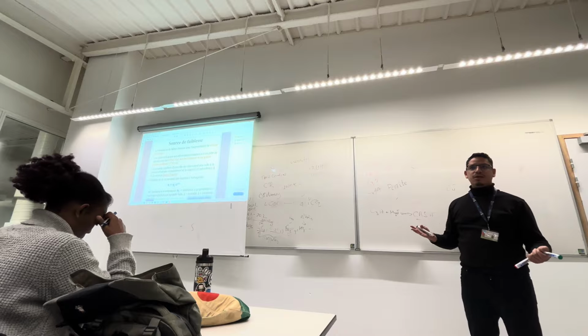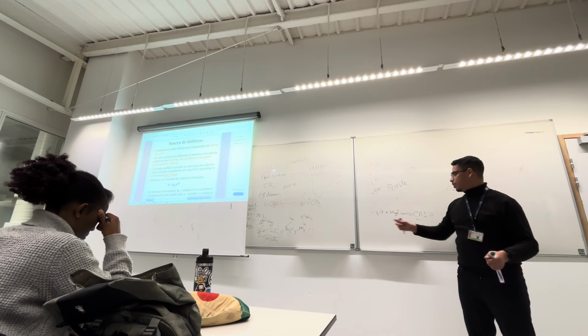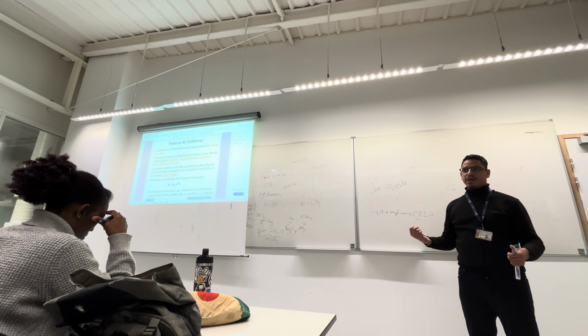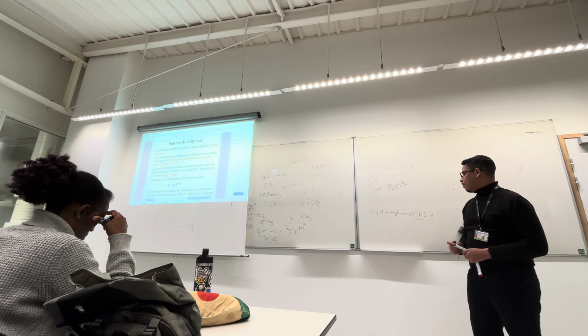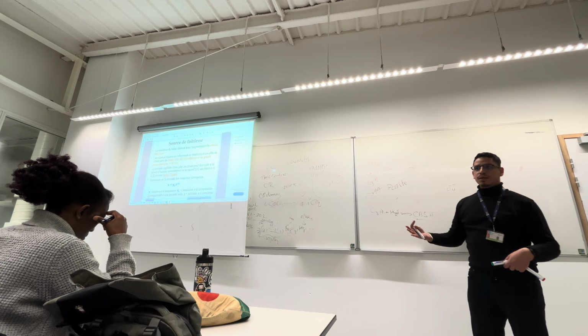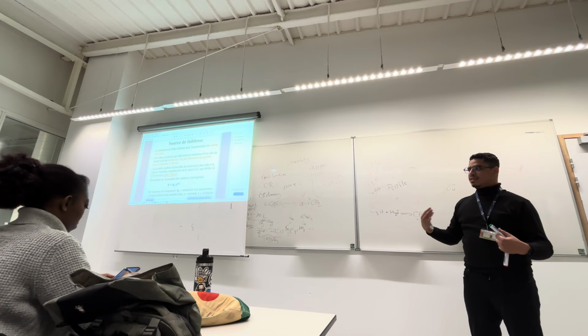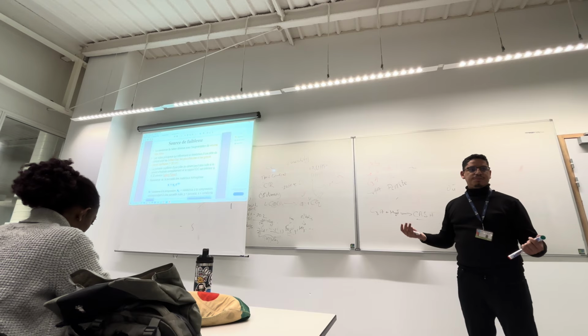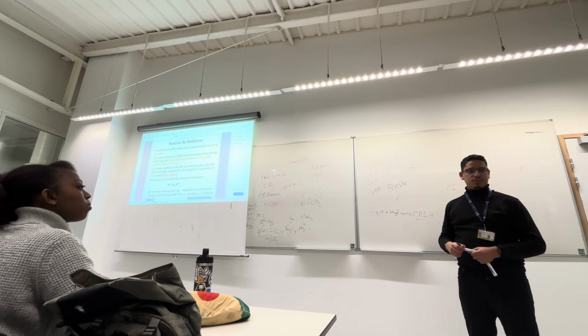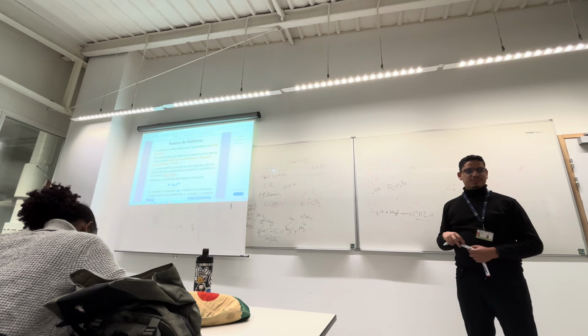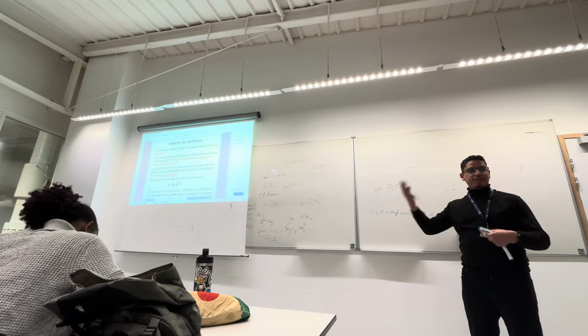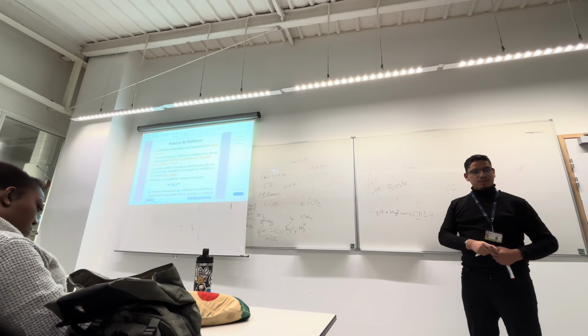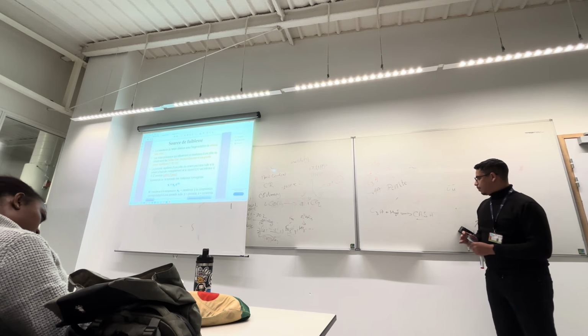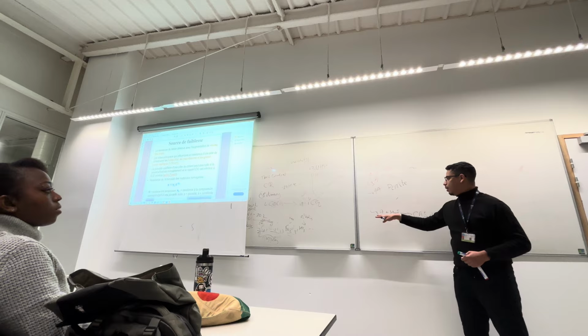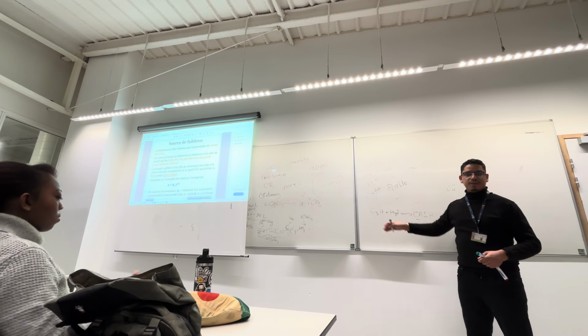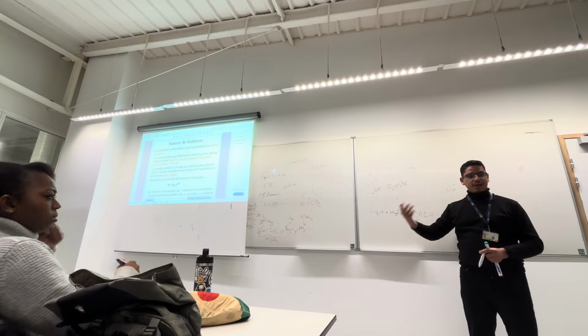So for the second reason, with the hydration heat, we need to reduce C3A to reduce the risk of chemical aggressive things. Okay? But from another point of view, the CSH coming from C3A is the best CSH. Do you understand the situation or not? It's a little bit confusing. We have a confusion between the durability. Yeah, so it gives CASH, and then when it's exposed to sulfate, it's going to react back to C3A. The problem in the study of C3A is that it allows a chemical attack.